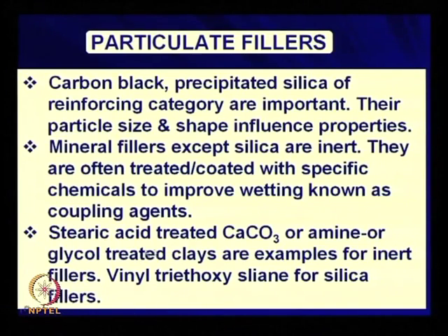Now, that can be improved if you can give a very thin coating to the filler particle. Here is an example of this stearic acid treated calcium carbonate. Calcium carbonate is an inert filler, but you can disperse it more easily in a hydrocarbon or organic polymer if you can make a thin coating of organic material.